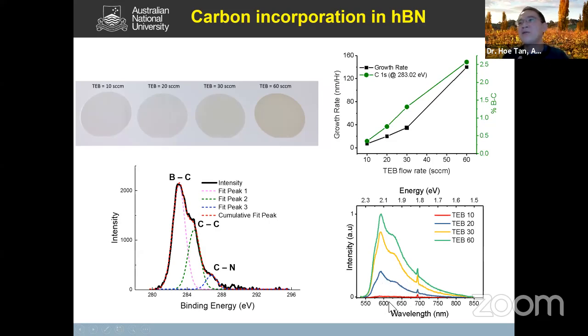Okay, so as I mentioned before, people are interested in HBN because it's got a large bandgap, it gives you deep UV emission. But unfortunately, because of all these impurities, we don't see this UV emission. We see visible emission. So when we started this project, we were a bit disappointed because we did not see any UV emission. But you know, sometimes this sort of occurs by accident. But what we found is that we can correlate this visible emission with the amount of carbon incorporation. As you can see here, if you are using a lot of TEB, then you have a lot of carbon incorporation, so this intensity increases. So essentially, this is like the defect or impurity emission that comes from HBN.